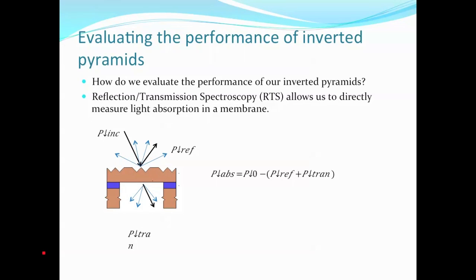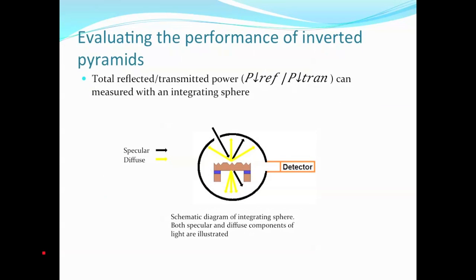Basically, you shine an incident power on the solar cell, and then you measure the reflected power and the transmitted power. The power absorbed inside the membrane will be the incident power subtracted from the sum of the reflected and transmitted powers. And these measurements can be made using an integrating sphere. And the membrane, you can see, is an excellent test platform for testing light trapping because we have access to the backside, so we can directly measure transmission losses.